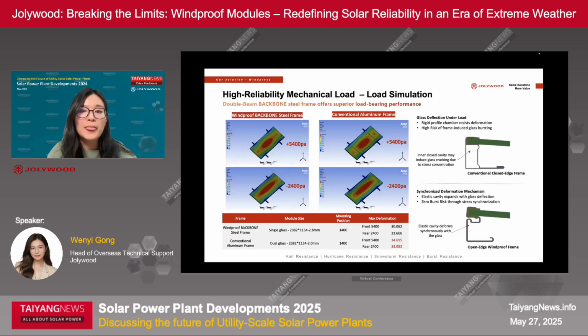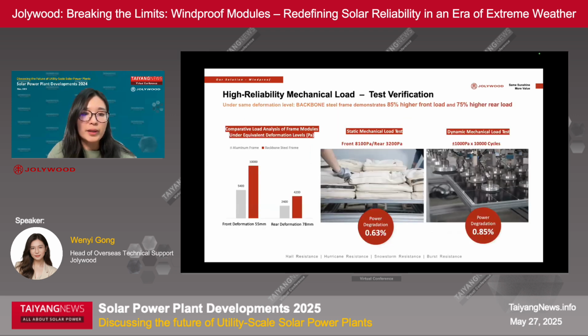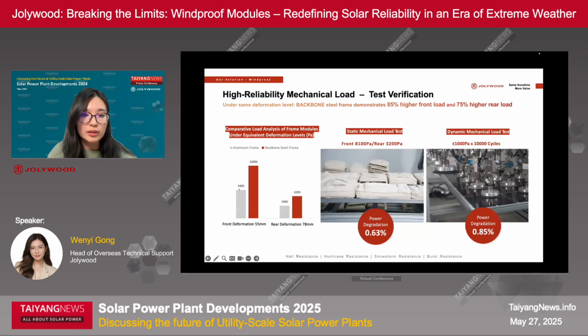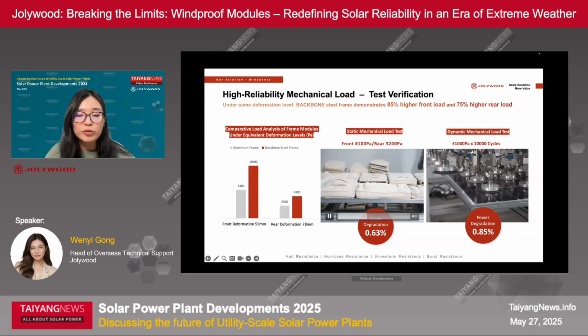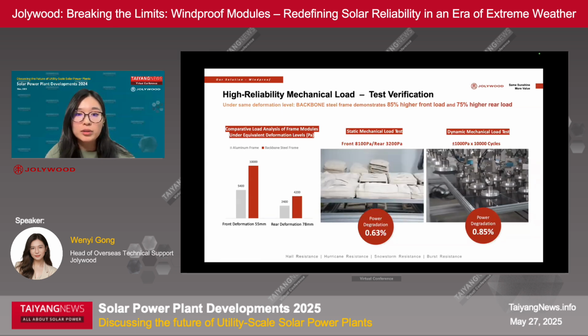Here we can see the test results. For the same level of deformation from the front side, the aluminum frame can withstand 5,400 Pascal from the front side and 2,400 on the rear side, while at the same level of deformation, the backbone steel frame can reach even 10,000 Pascal from the front side and 4,200 at the rear side. So for some sizes of the windproof module, it can pass the 8,100 Pascal static mechanical load test and also 10,000 times the dynamic mechanical load test.